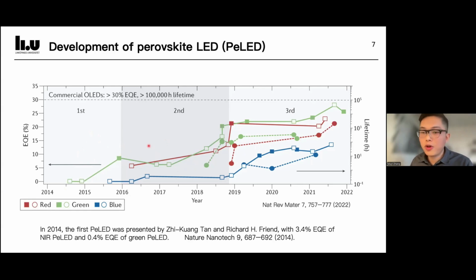So this beautiful figure shows up to the year of 2022. Green had taken the lead, reaching over 25% EQE and even cracking the 10,000 hour mark for the lifetime. But blue is still the most challenging. Just like in OLED, they demonstrate a lower EQE and lifetime. But the progress is also clear. And we believe with more people working on it, maybe things can be accelerated.